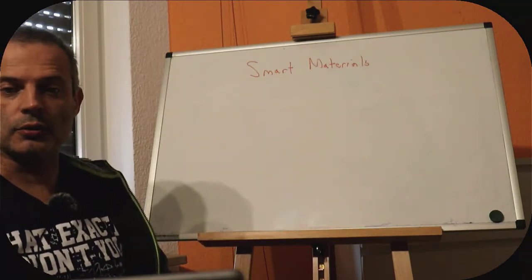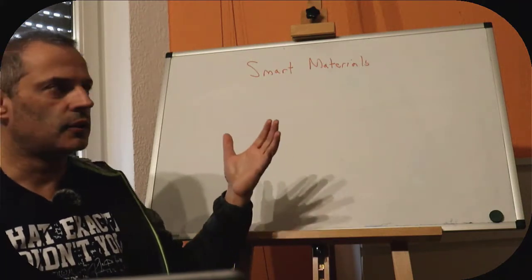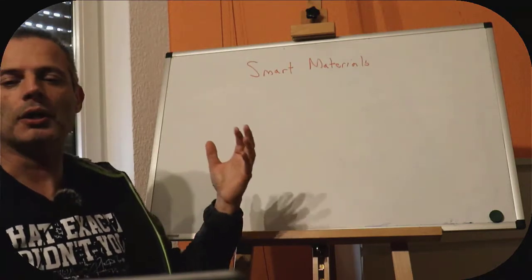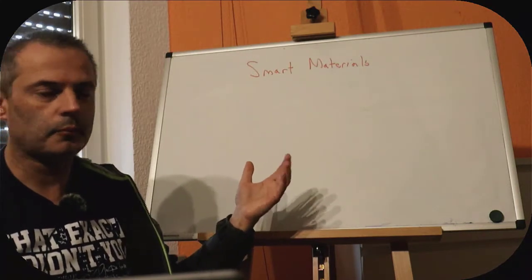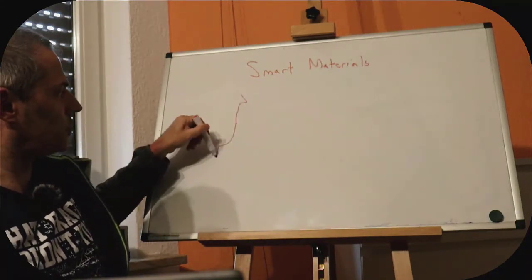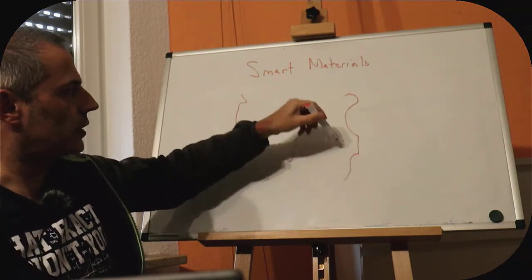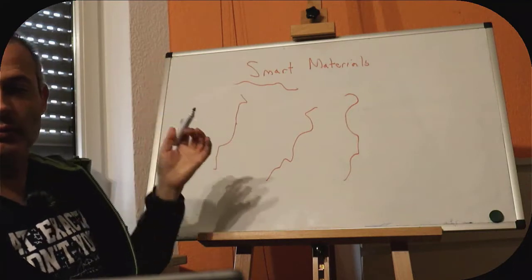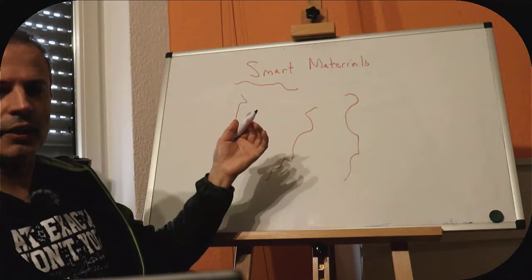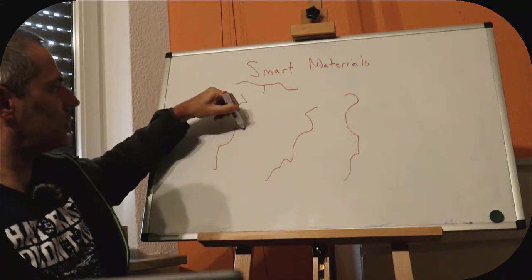A good simple example would be a type of gel that thickens in the presence of calcium ions, behaving very much like blood clotting would. So if we imagine that, we can think of something that will bind to calcium. We've got some kind of polymer, and it will have to be dissolved in water. Otherwise, it won't be a carrier of ions, and secondly, it won't be very easy to mix. And then we can have groups on the side that attach to calcium.